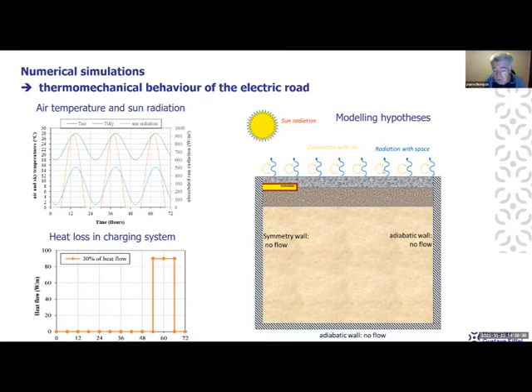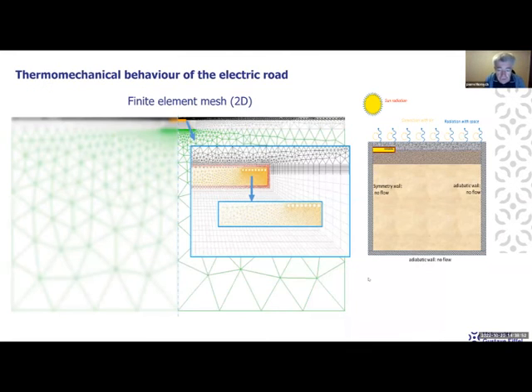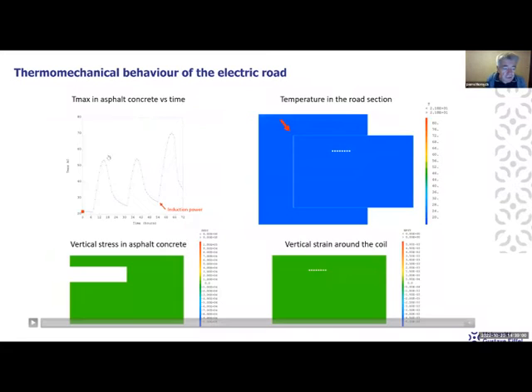So this is the kind of model that we simulated. We simulated it in 2D. And here you can see the block with the coils and the pavement layers, and here the subgrade. So here is the finite element mesh. It was a 2D finite element thermomechanical calculation. And so we simulated these cycles. First only the temperature cycles, and then we added the induction power, and we simulated also the heat increase due to the charging. And so we tried to predict the stresses and the strains and the temperatures in the system.